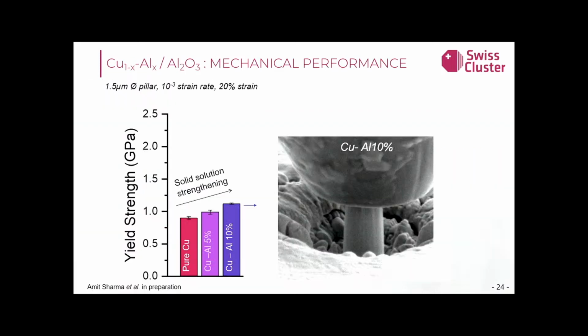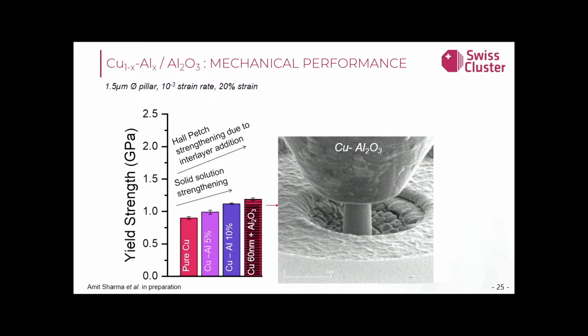We then do mechanical compression, so pillar compression. We mill out these pillars of defined sizes, and in situ in the SEM, we do this pillar compression. You can see the effects. This is measuring the yield strength of pure copper, and as we add aluminum, naturally we have solid solution strengthening, so keeping up with theory.